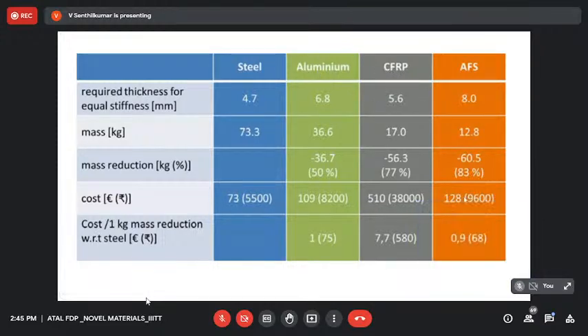When you do that for CFRP, carbon fiber reinforced composites, you can see that the thickness has to be increased to 5.6, but you see how much mass is used for steel. Here we know that the density of steel is 7.85 and for aluminum it is 2.7, and CFRP is further less than that. Normally it is only 1100 or 1200 kilogram per meter cube. For this aluminum foam structure, normally the maximum relative density will be only 28 to 30%. Even though aluminum is 2.7, here we are getting only 400 to 500 kilogram per meter cube. So just imagine how much weight it will occupy.